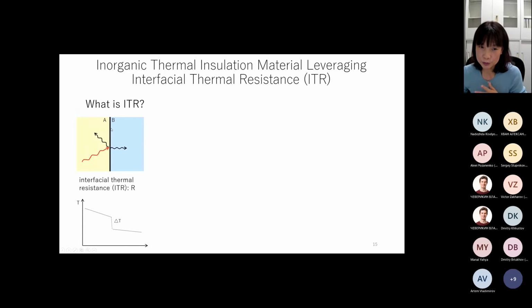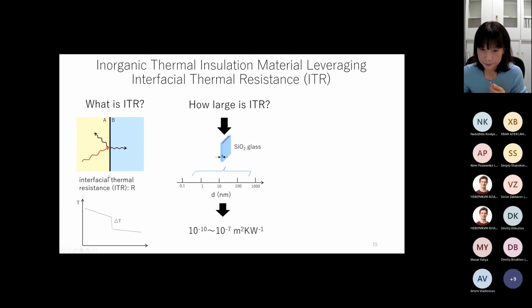That's when we have two materials combined together, there will be an interface in between. And when heat flux passes this interface, the energy carrier, phonon or electrons, will be reflected or scattered. So only a part of them can pass through it. So it causes an extra thermal resistance. We call it interfacial thermal resistance. And if we look at the temperature of this system, we can find a temperature jump at the interface.